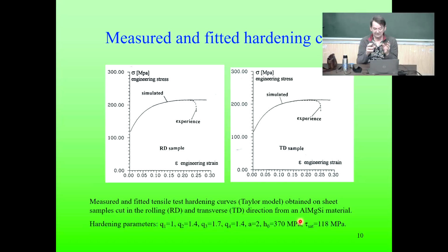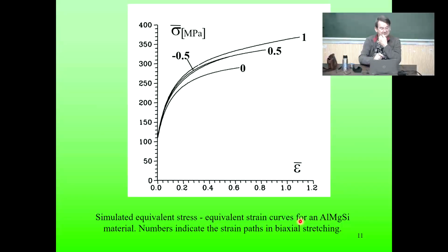You're not going to have one single curve for all deformation modes with equivalent stress and strain, of course, but they will depend on the strain path. Here is the simulation, which shows minus 0.5 is the tensile testing, which was perfectly reproduced. And then if you plot it for the other strain modes, when rho is 1, that is equibiaxial stretching. And this is 0.5, between plane strain and equibiaxial. It depends on the strain path. It comes naturally from the simulation.